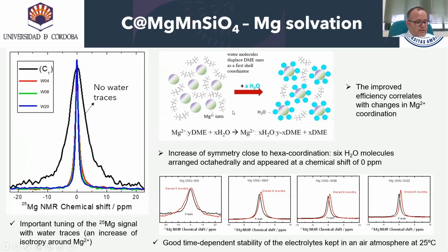25Mg NMR detected an increase of isotropy around magnesium ions in the presence of water traces, black no water traces, in color different water. This fact can originate an increase of the electrolyte solvent mobility due to ion pair formation in the water-containing electrolyte. The result suggests an increase of symmetry close to hexa-coordination because of the solvated structure of magnesium with 6 water molecules appear at the chemical shift of 0 ppm. Most probably, the water molecules displace the DME ones as a first shell coordinator.